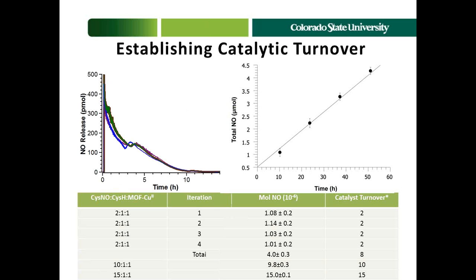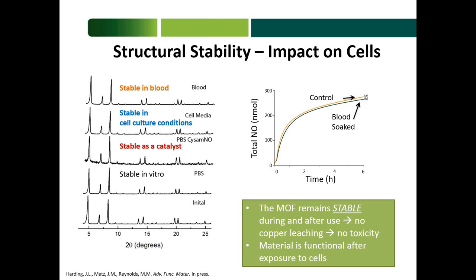We can then take these crystals and we can demonstrate catalytic turnover time and time again. The picture on the left is basically taking out the crystals, brushing them off, putting them back in, and looking for the reaction to occur. The kinetics of this does not change over time, so we get prolonged potential release of nitric oxide at the surfaces of these devices. These materials remain structurally stable, which is important because thinking about their impact on cells,